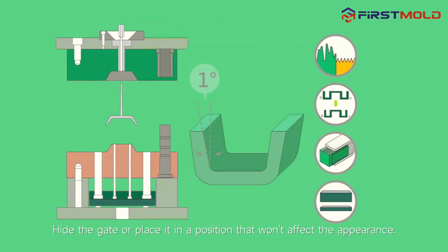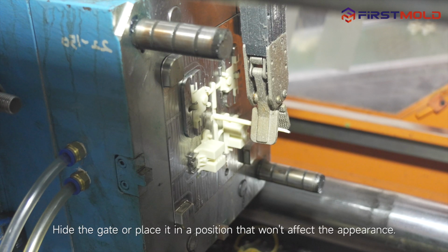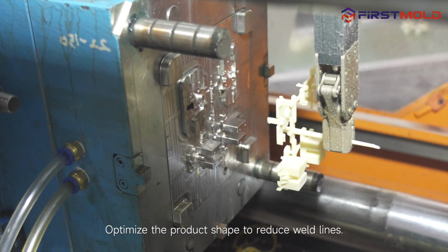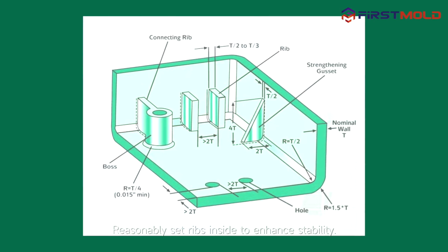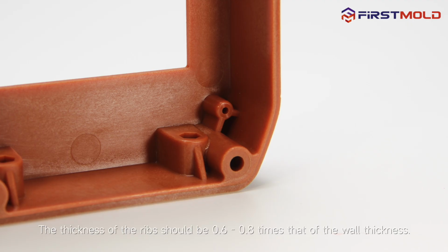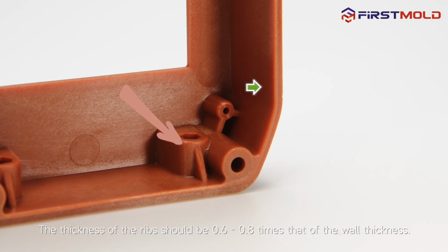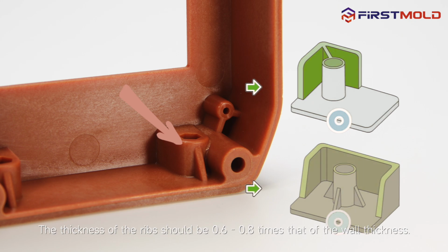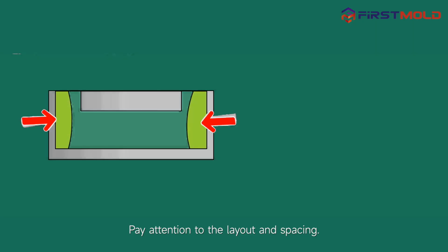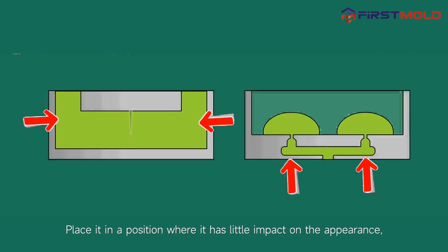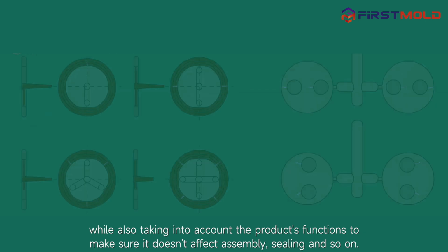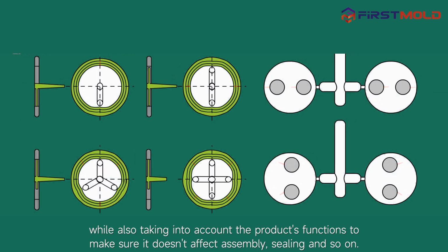Hide the gate or place it in a position that won't affect the appearance. Optimize the product shape to reduce weld lines. Reasonably set ribs inside to enhance stability. The thickness of the ribs should be 0.6 - 0.8 times that of the wall thickness. Pay attention to the layout and spacing. Place them in a position where they have little impact on the appearance while also taking into account the product's functions, to make sure they don't affect assembly, sealing, and so on.